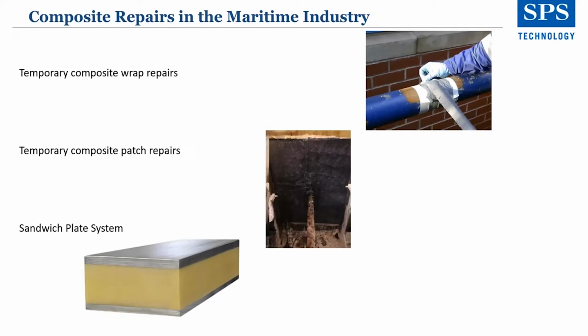Temporary composite patch repairs feature an application of carbon and glass fiber mixed with epoxy resin or adhesive to a damaged surface. By curing, the resin hardens and permanently bonds to the surface, impregnating also the fibers that reinstate the strength of the damaged part. This creates a solid new layer of material that provides full water tightness. These repairs have been around again, probably about 35 years.